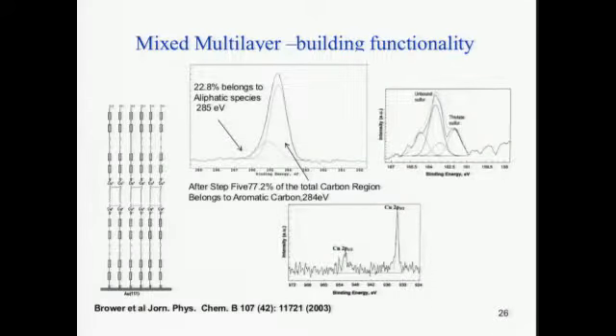And by XPS, we could easily look again at the sulfur region. Here I see both the thiolate and the unbound sulfur, and there is copper present. And there are actually 2 different carbon species: the aromatic carbon species and the aliphatic carbon species. Taking all this together, specifically looking at the oxidation state of copper, I think I didn't say that. Did I say that? I'm seeing copper in +1, by the way. So this is what we propose is the final structure using this methodology.